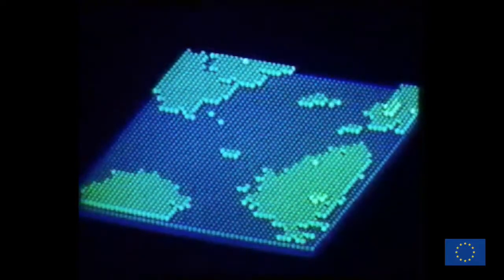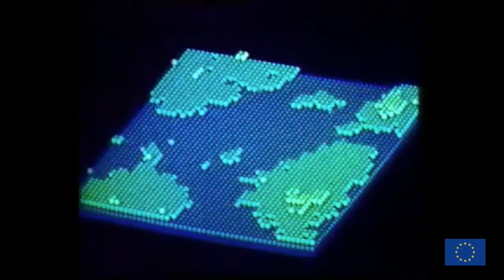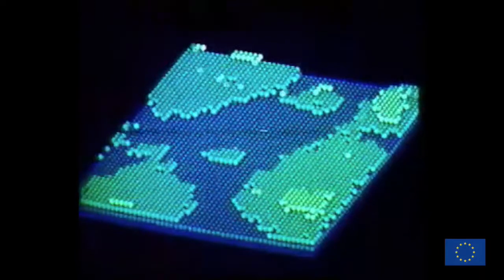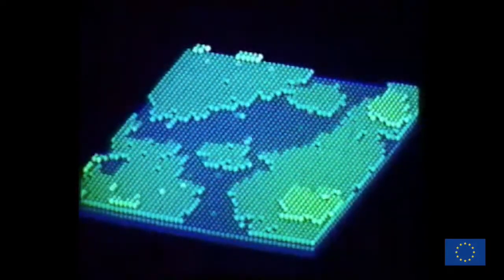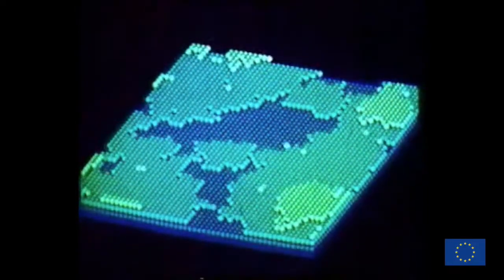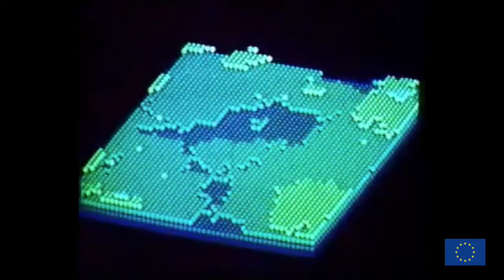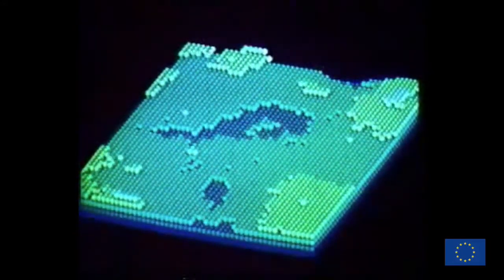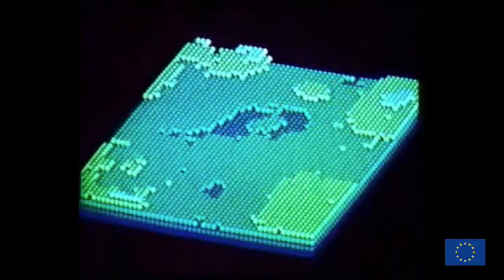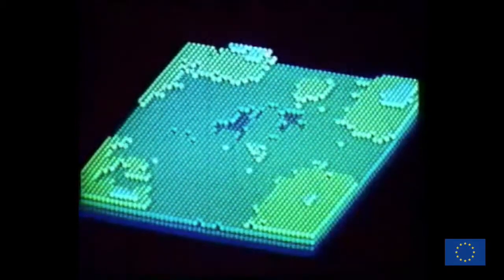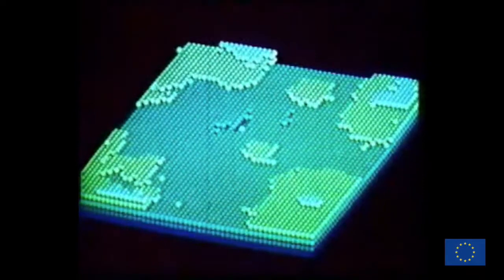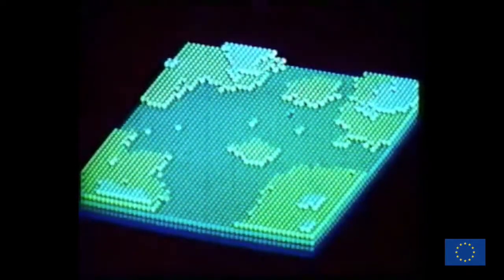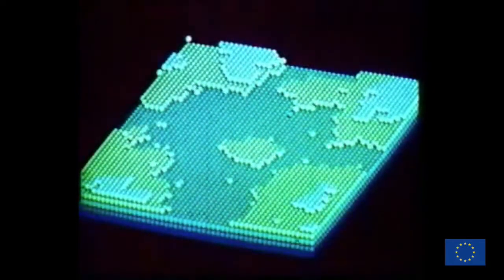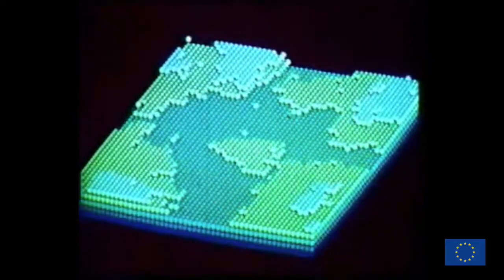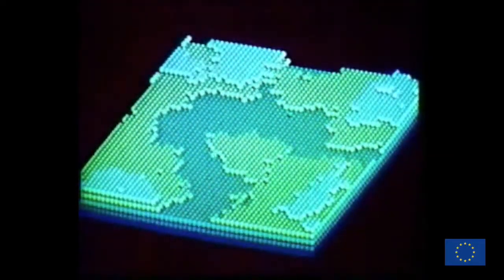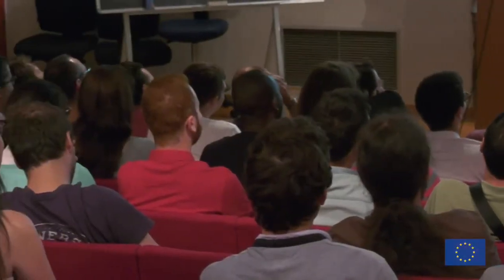What you can also see here is that on some of the existing islands, you already have a second nucleation site starting. So even though you have started from a perfectly flat crystal, you already start seeing some topology forming. It's inherent in the way this thing grows. And so in the end here we have almost full coalescence of the first layer, and then it will just continue with the next few layers. I did not point it out, but the critical size for one of these islands under these conditions, let's say it's about 10 to 15 atoms in this simulation, which will be different in the next movie where we will have a different overpressure. Okay, so this was movie 1.